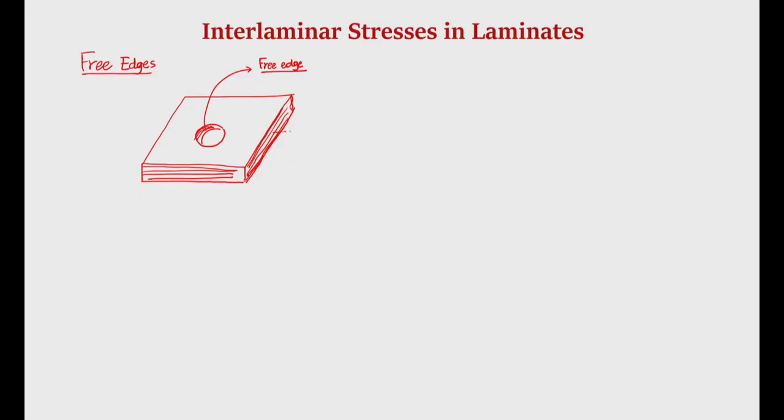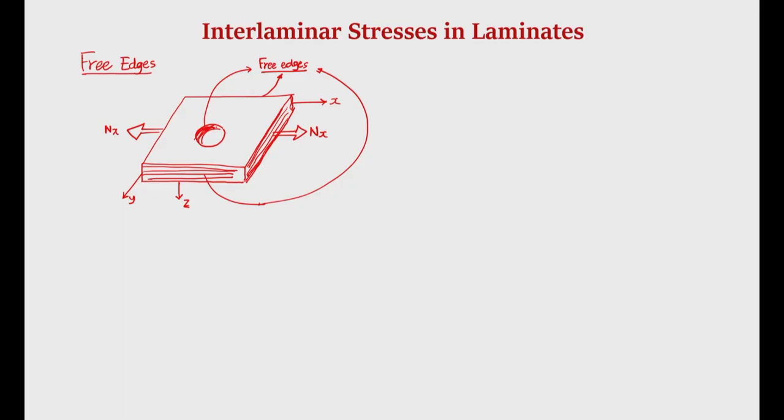Okay. So, suppose this is your x, this is your y, this is your z. So, if it is only subjected to suppose nx, therefore, these are anyway the free edges. In addition, suppose there is a hole, this also forms a free edge. So, this phenomenon of development of interlaminar out of plane stresses will also be seen at this free edge of the hole, along with the free edges of the laminate. Okay.